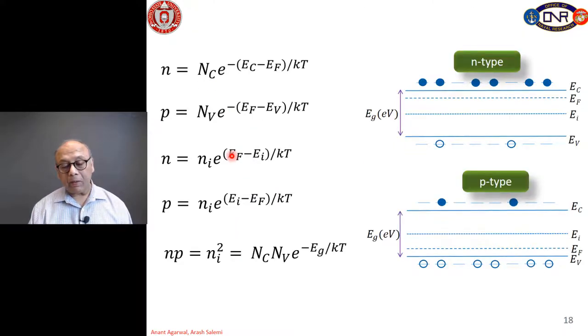So basically, let us summarize that we have n-type material where the electron concentration is described by Nc times exponent of negative Ec minus Ef over kT. So that essentially means that as we make the material more and more n-type, the Fermi level moves closer to the conduction band edge, and my free electron carrier concentration in the conduction band increases.